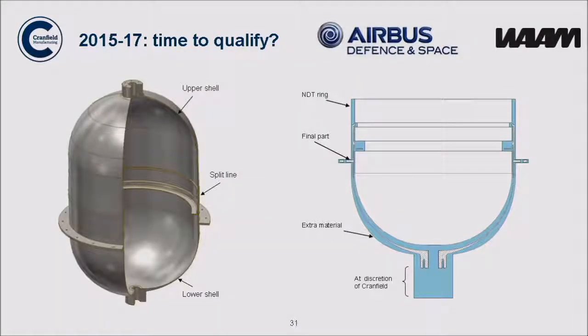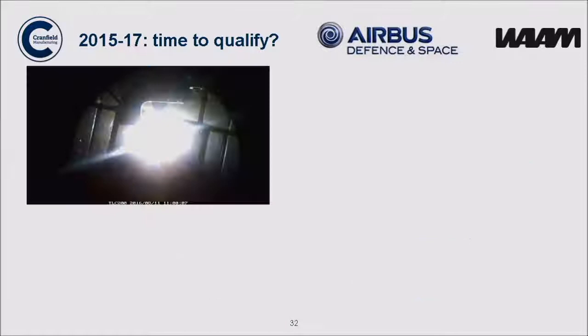So how far have we got in terms of building parts and working towards real applications? This is probably the closest one that we have at the moment. This is a satellite propellant tank we developed with Airbus. It has these two halves, and you can see these flanges on either side of it. The current manufacturing process is to take a 40mm thick forging, machine it all down to round about 1 millimeter thickness, and then weld them together. So this is incredibly expensive, as you could imagine.